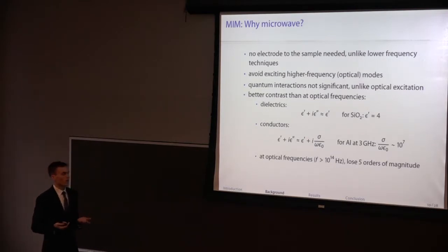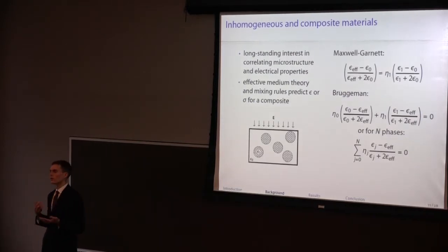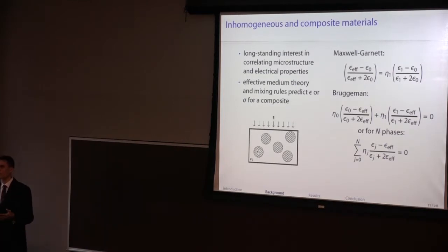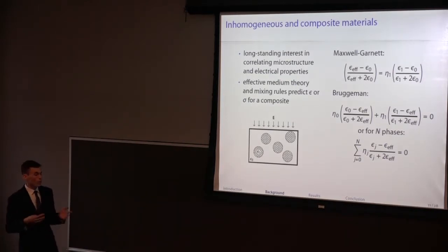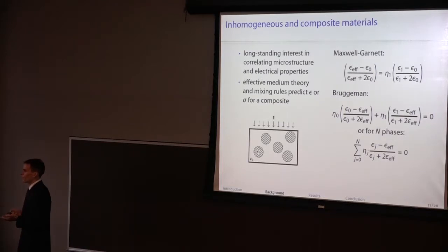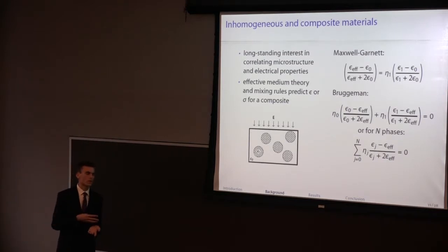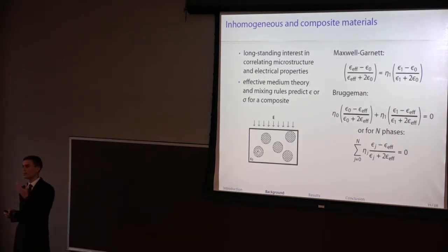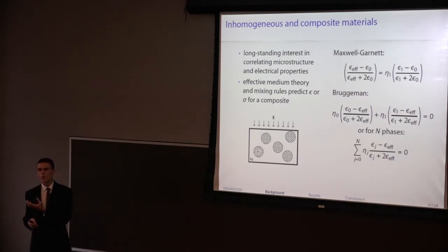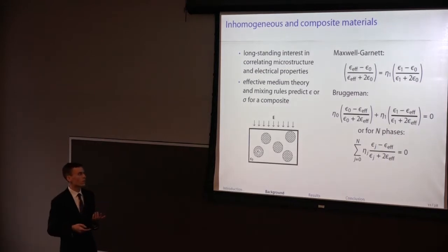So assuming then we are happy with the microwave regime, how are we going to model the interaction of that microwave field with the inhomogeneity in the sample? It's actually a longstanding problem. One of the conventional approaches to dealing with that problem is a process of averaging, of homogenization. Is there a model homogeneous material that I can use to predict the behavior of my heterogeneous material in response to some applied field? That type of analysis has led to simple formulas like this well-known Maxwell-Garnett formula, which relates